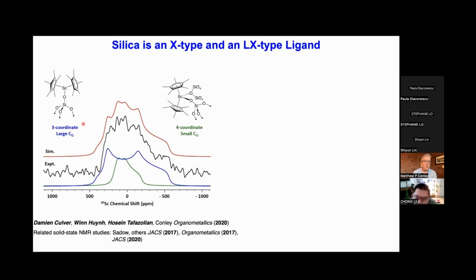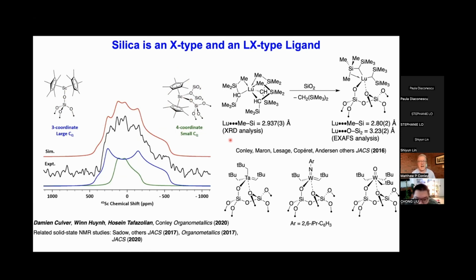Those two different sites are reflective of the scandium being in sort of a low symmetry environment or a higher symmetry environment. The smaller CQ is reflected in the more tetrahedral geometry at scandium for this 4-coordinate species, and the larger CQ or the broader signal is associated with this 3-coordinate scandium species. The other way you can get information about silica behaving as this pure X-type or this LX type ligand is looking at how other features change when you react your organometallic with dehydroxylated silica.